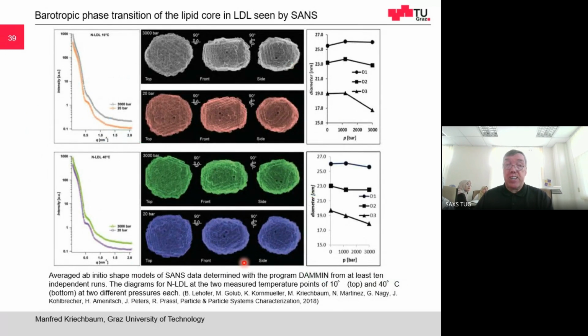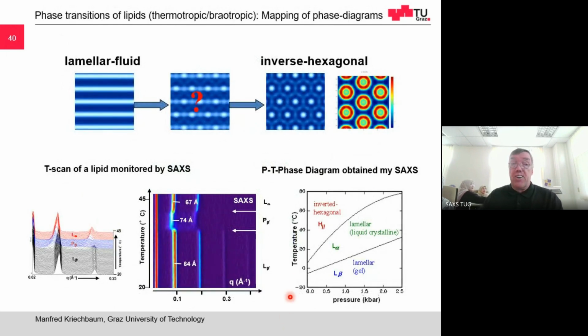And additionally, we also did high pressure with neutron scattering. Neutron scattering is a different technique. It's the same principle, but you're using neutrons instead of X-rays. And we also see the changes from 1 bar, so the different dimensions of this ellipsoid with high pressure. So there are slight changes also in the enveloping protein structure.